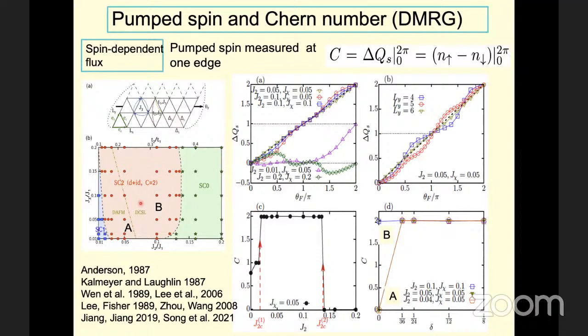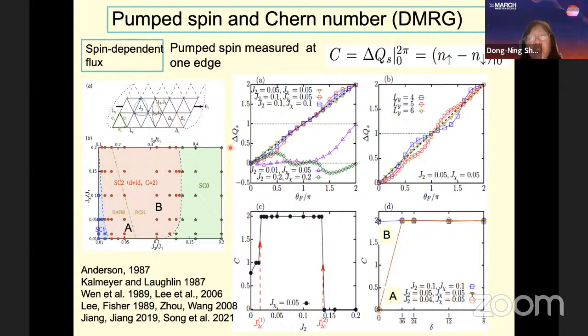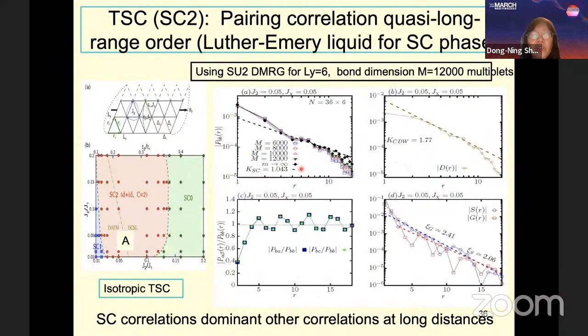Okay, so that phase diagram is obtained based on combined simulations. One is calculating topological spin pump, which gives us the Chern number. The second simulation, which allows us to determine the phase diagram, is the pairing correlation. The pairing correlation shows power law decay, and for the topological superconducting phase, it can have pairing which is near isotropic. As illustrated in this figure, we're plotting the pairing correlation for pairs along different nearest neighbor bonds.